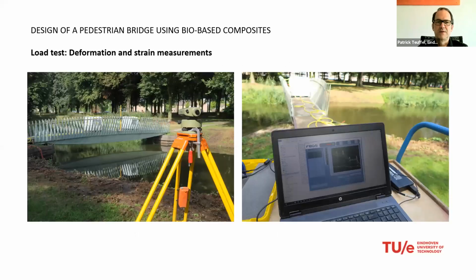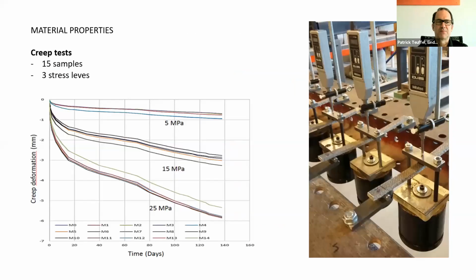So once in a while, the colleagues from the sensor company come to our campus and plug in their computer, and then we have either steel weights or water tanks or students walking over the bridge, and we can measure the strain and also the deformation of the bridge in real time. And parallel to that, we also did some creep tests in our lab to understand the long-term behavior of that material, because obviously creep is an issue not only for natural fibers, but for composite materials in general.